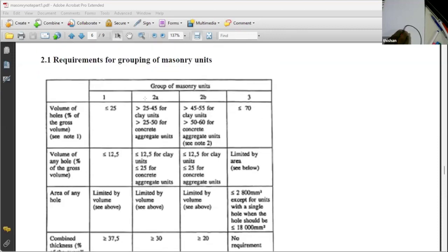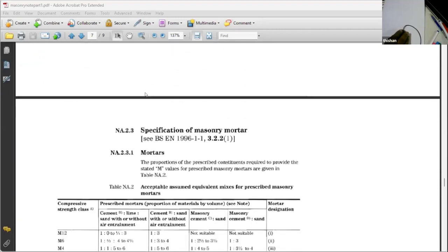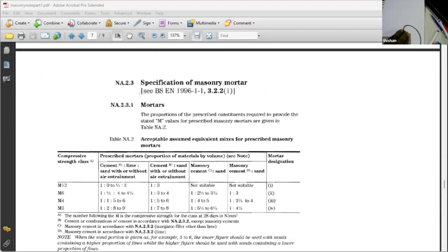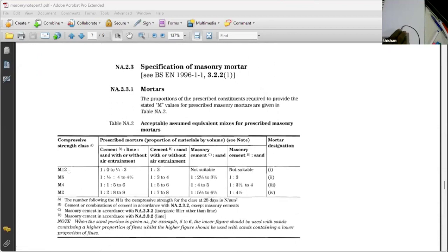So what you have to keep in mind is we are looking at group of masonry, which is 2A. Right. Then it says, okay, we have to use certain mortar. And generally we use M2 mortar or M4 mortar or M6 mortar or M12 mortar. But in Sri Lanka, generally we use M4 mortar, which is 1:5 or 1:6 cement sand mortar without air entrainment. So when you use 1:5 mortar, generally we can get a strength of 4 megapascal. So that's why we call it M4 mortar. The expected strength is 4 megapascal. Right?